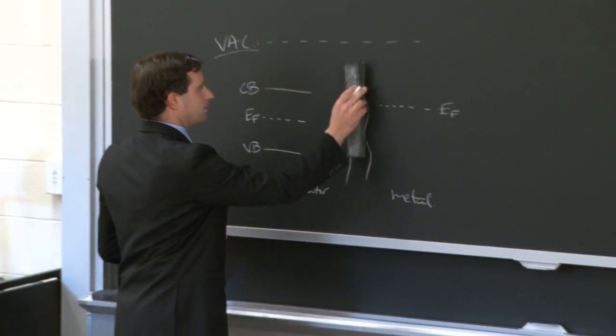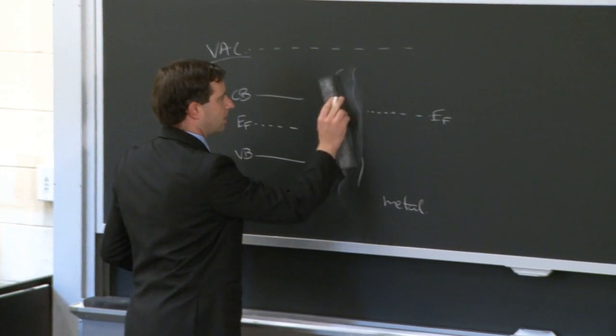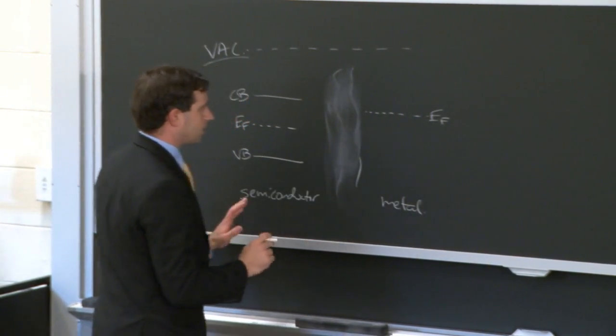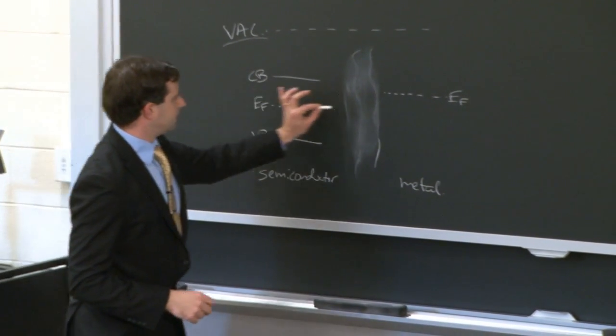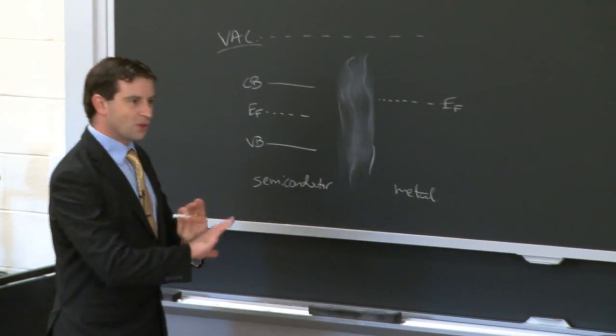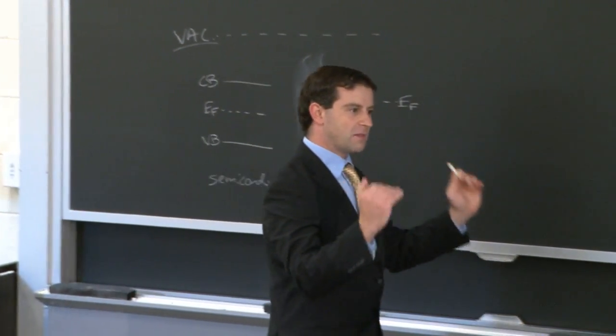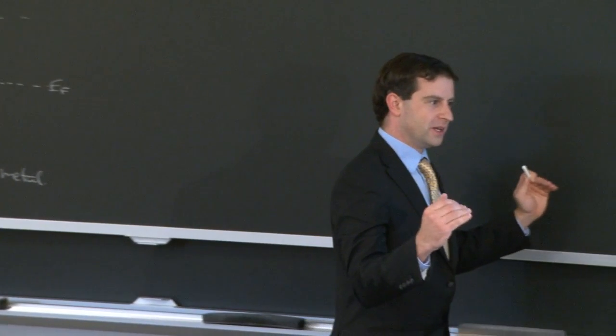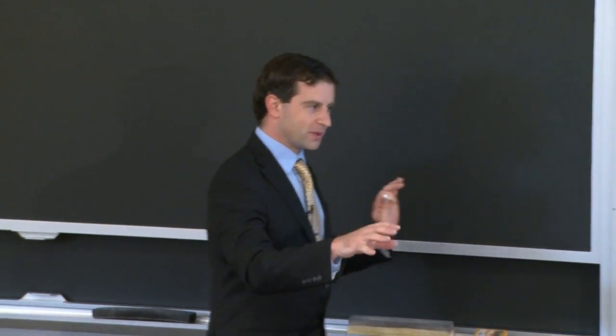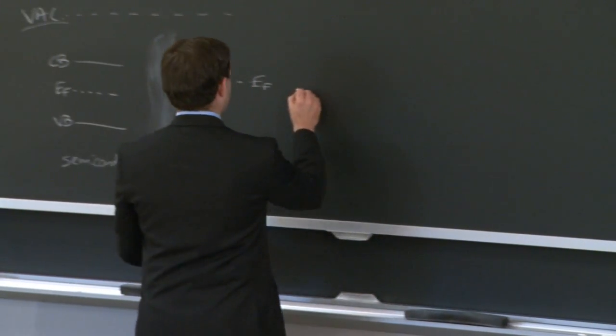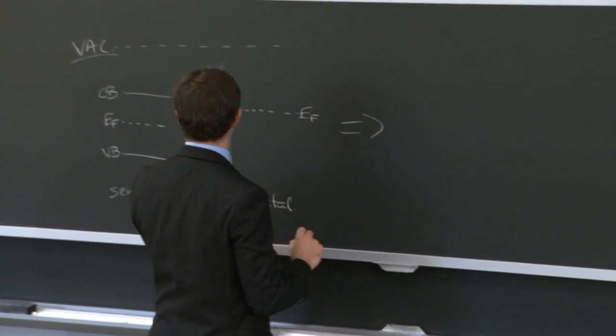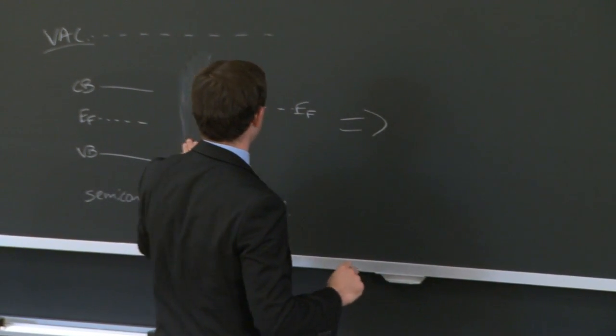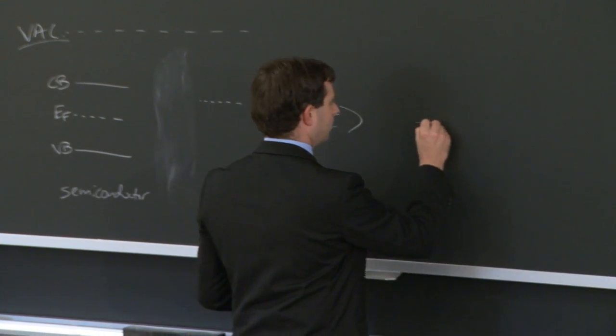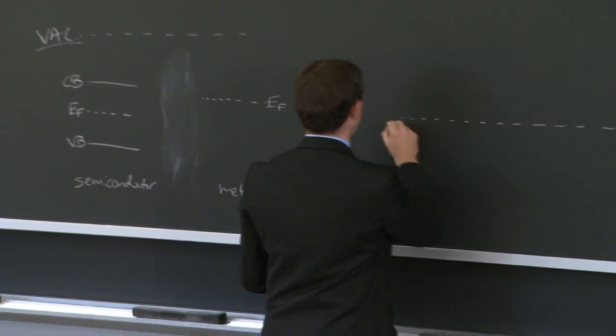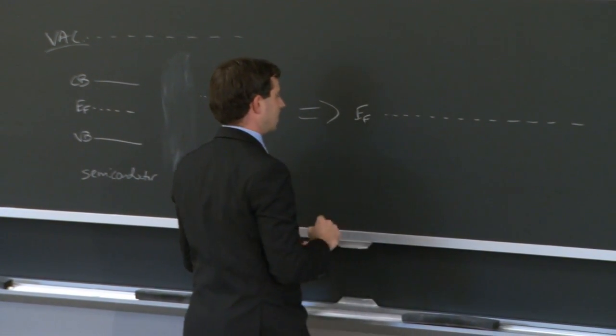Well, step one is to remove that imaginary barrier in between them. And now you begin to look at this and say, well, if they're in good electrical contact, and there's no resistance throughout the material, the chemical potential should be identical all throughout the material, from left to right. And so now I merge into phase two, which is to say I've removed this barrier in the middle, and now my Fermi energy is going to be equilibrated throughout. So my E sub f is going to be the same throughout.